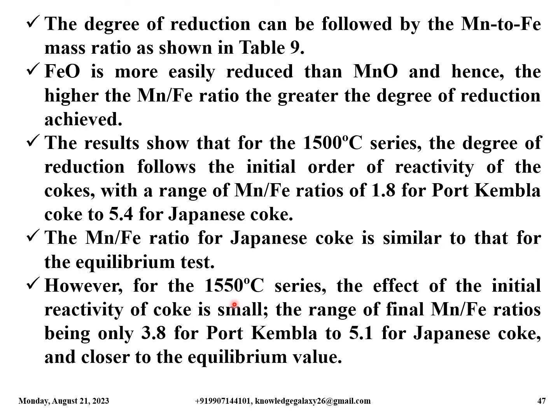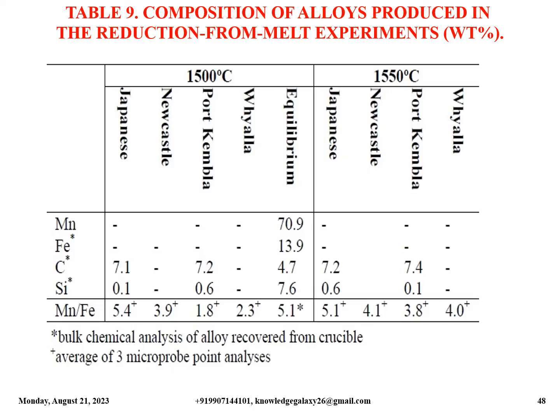However, for the 1550 degree Celsius series, the effect of the initial reactivity of coke is small, the range of final Mn by Fe ratios being only 3.8 for Port Kembla to 5.1 for Japanese coke and closer to the equilibrium value. So this is the table which depicts the details which I have just explained. Composition of alloys produced in the reduction from melt experiments in weight percentage. You can pause the video and observe the table contents.